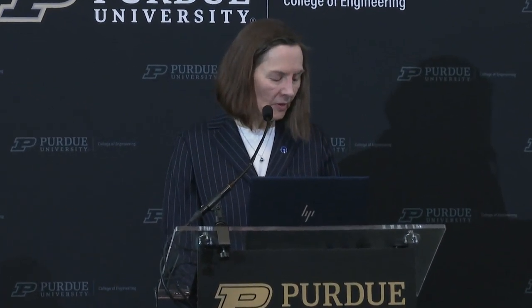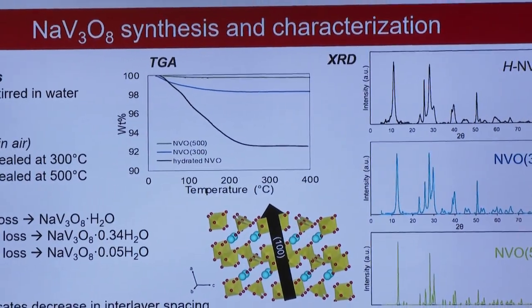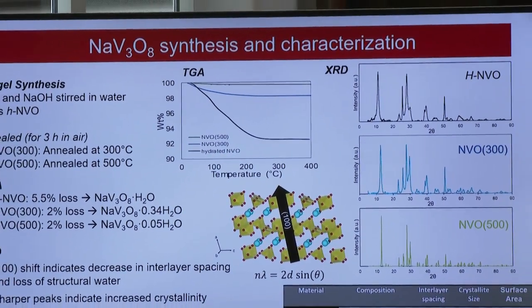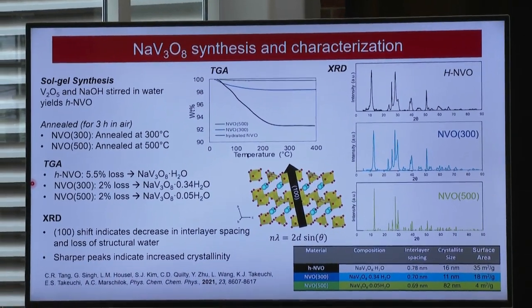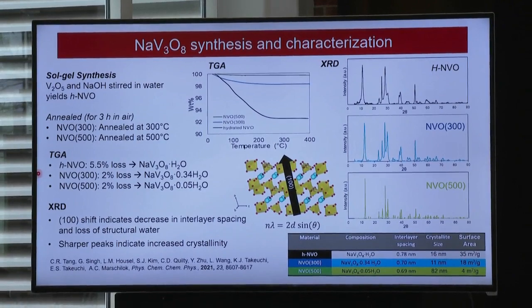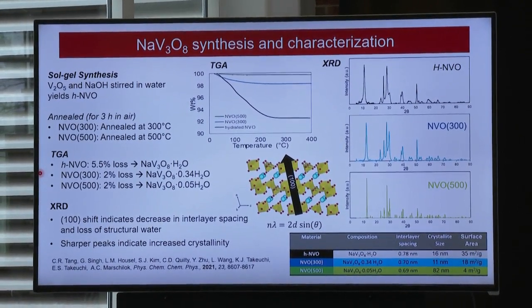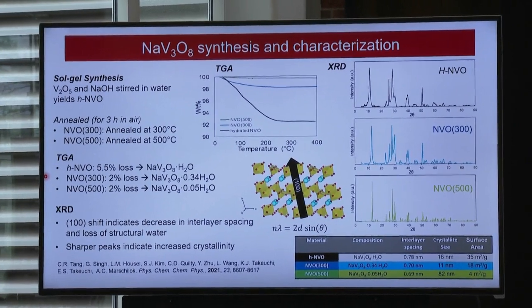So the first material we looked at is sodium vanadium oxide, or NVO for short. It's a layered structure. The sodium makes pillars, so we thought that it would be effective in storing zinc. First thing we did was actually synthesize the material. We use a sol gel method. This is an aqueous method that's readily scalable. And we were deliberately controlling the water content. Our hypothesis was that the water content between the vanadium oxide layers would be an important contributor to facilitating zinc ion mobility between these layers.